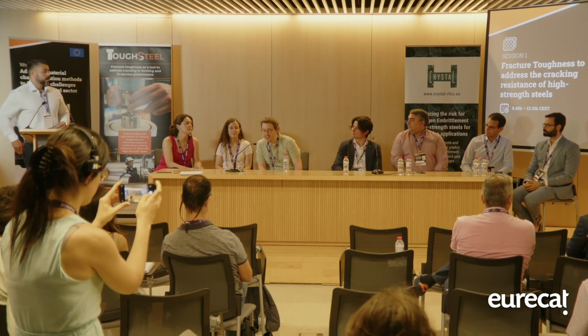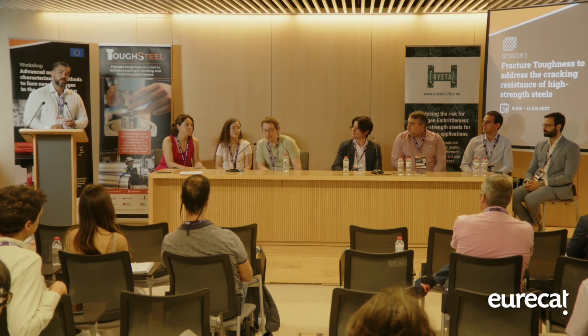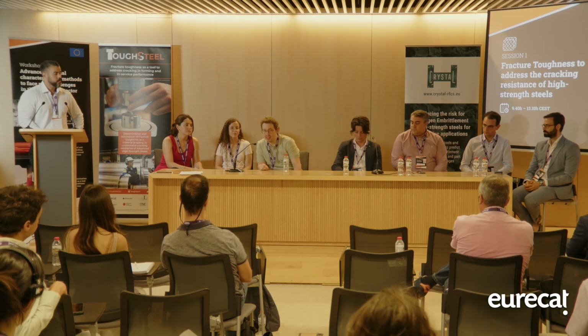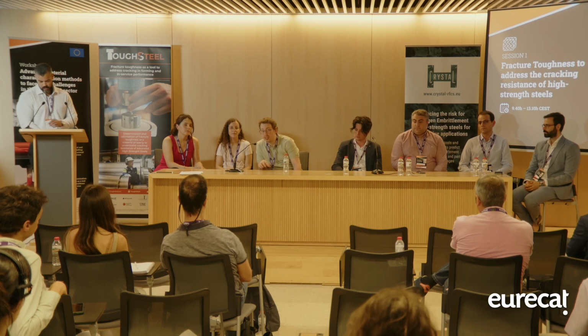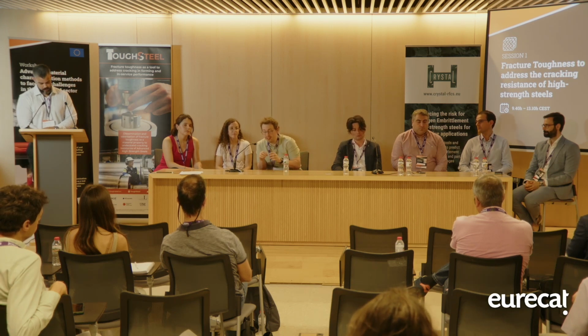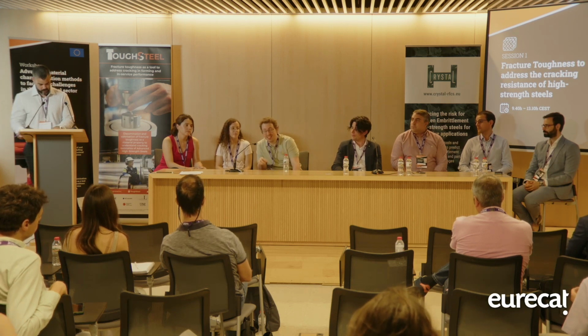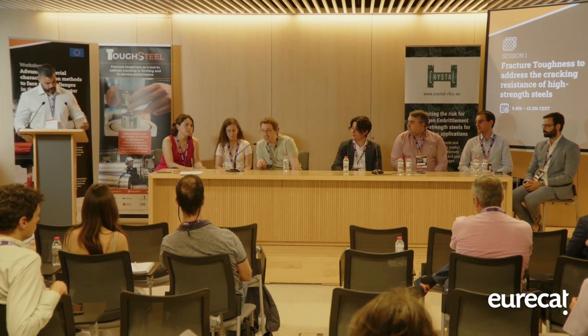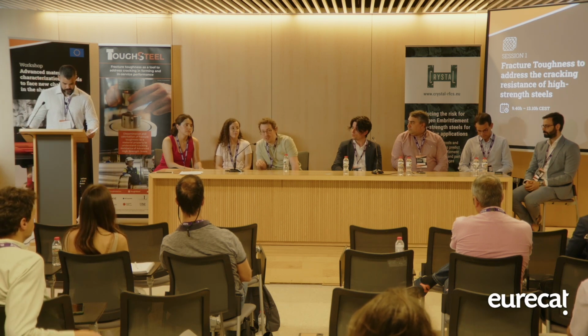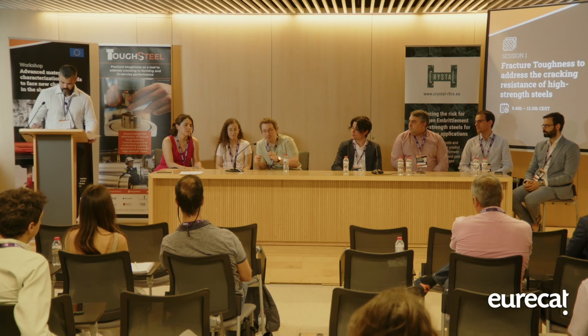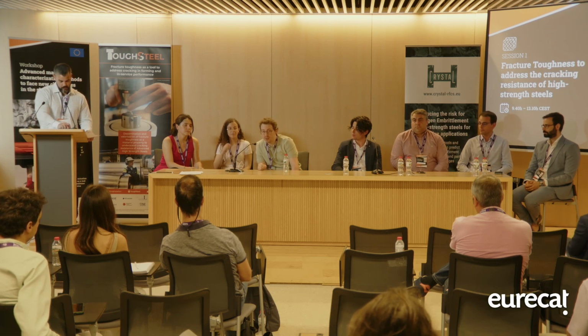So I tested one of the materials at one strain rate, and it was 0.5 meters per second crosshead speed. So the local ductility, local fracture, the strain rate close to fracture was capped at 1,000, probably higher locally by the crack tip. So it's really high, close to fracture, when it starts to propagate.